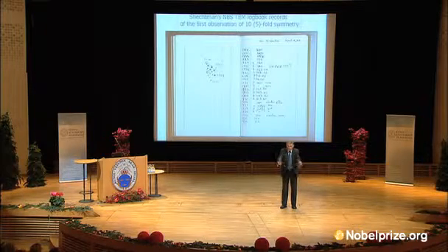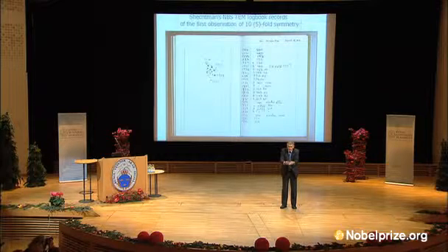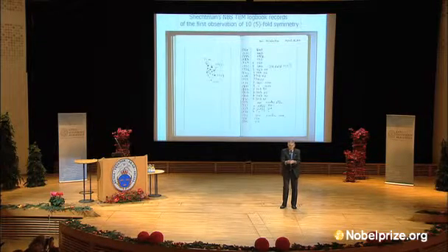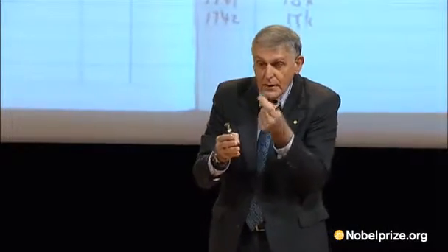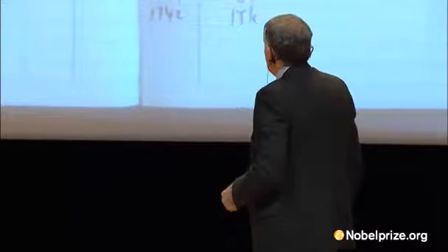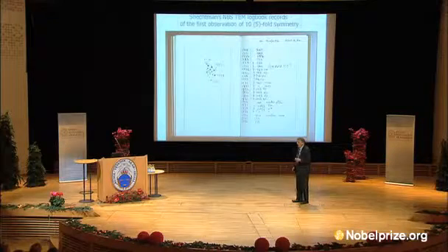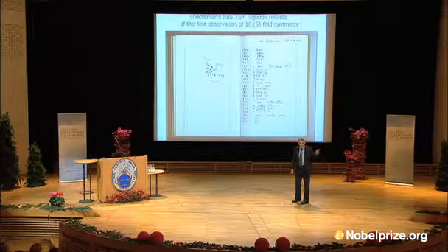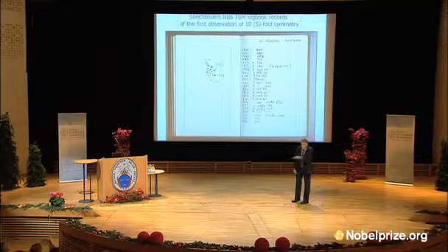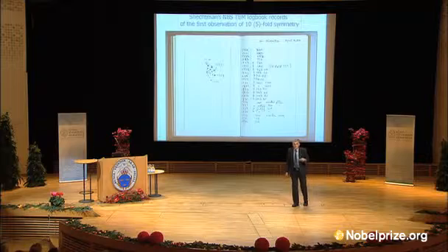Microdiffraction means that you converge your electron beam onto a spot, and from that very little tiny spot, you take the diffraction pattern. And if there is a tiny, very small twin, just one, then I will get an ordered periodic diffraction pattern, which will show me that there are twins, and there's nothing else there. No twins were found. So by now I knew that I have something very special. I didn't know what it was. But I knew from day one that there were no twins. And this becomes important later on because the opposition said up until 1994 that these are twinned crystals, and I knew from day one it was not.